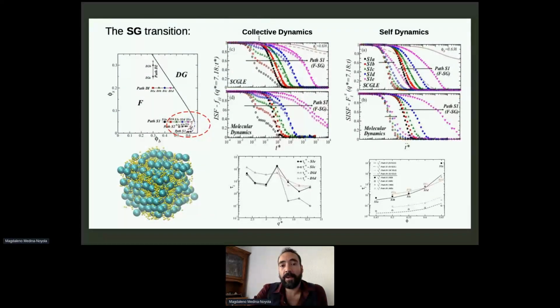One can compute, for instance, the collective dynamics and the self-dynamics of this system approaching this transition to recognize that there are different patterns. For instance, the collective dynamics of the whole system becomes coupled, and both species undergo, in terms of their own relaxation times, a slowing down, as described by the intermediate scattering function corresponding to each species, which can be resolved, as Marco, I hope, explained. But there is also a dynamical decoupling of the big and small particles relaxation times in terms of the self-intermediate scattering function and properties such as the mean square displacement, which allowed for the characterization of the localization length. And then one can also access relaxation times, just as Marco presented for all the other systems that he was characterizing, to notice coupling or decoupling depending on which state one approaches.